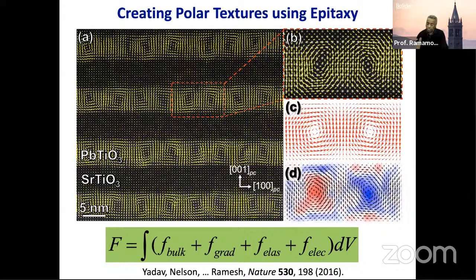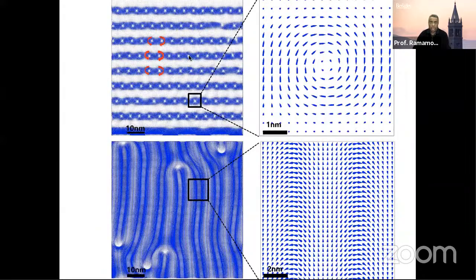So when we saw this, we said, oh, this is really fantastic. How does one really understand the properties? As it turns out, this was completely unexpected. Nobody expected to form these kinds of vortices. Our theory colleagues, with phase field calculations, showed that indeed they do form. These are indeed the ground states. You can see one of these vortices rotating like so. This looks very symmetric. If you look at it from the top, it looks very much like a bunch of tubes. I'm going to show you images of these tubes in just a second. And you can look at the dipolar distribution. This looks something like this. These are the dipoles going in and out of them. And that's what this picture is showing.